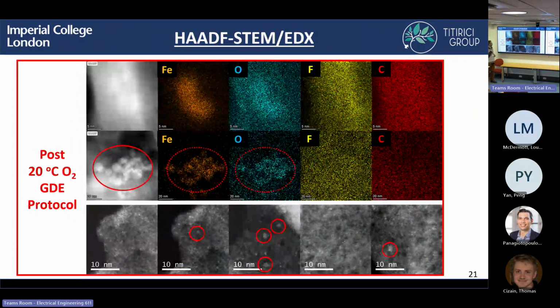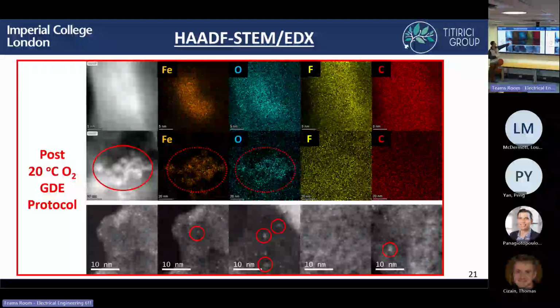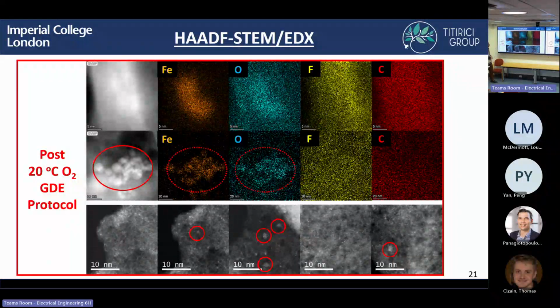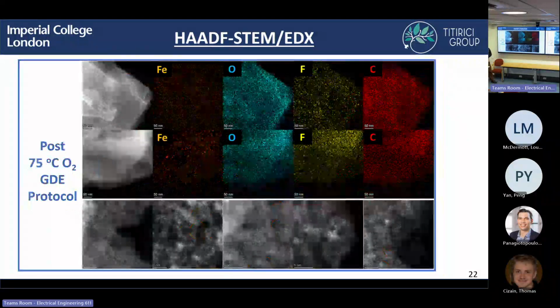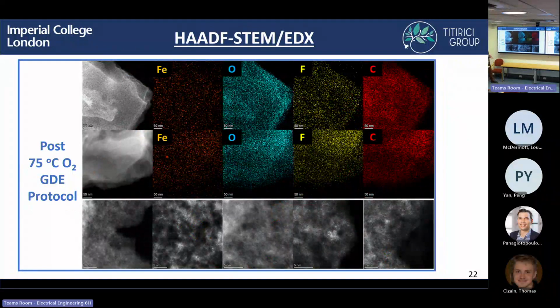Whereas after the protocol in oxygen at 20 degrees, we see very clearly that there's a high concentration of these iron oxides, as we see the overlap of the iron and oxygen in EDX. And we see as well more clusters of very, very small clusters of iron in the material. And surprisingly, when you look at then the measurement at 75 degrees in oxygen, we see that there doesn't seem to be many visible iron particles within the catalyst, whereas we saw a much bigger degradation in the gas diffusion electrode performance. But I'll explain why this is in a moment.